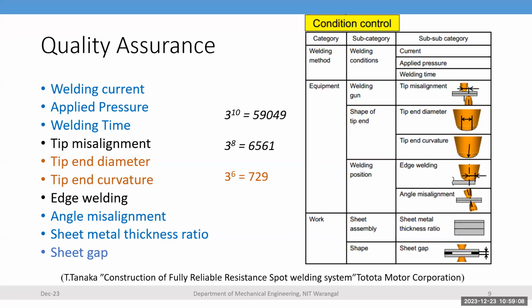Then, with reference to the workpiece sheet assembly, the sheet metal thickness ratio also affects the heat generation of the individual plate. And shape, sheet gap. If there is misalignment between the two sheets, air occupies the space between them. That air is a bad conductor of electricity, so heat is not transferred to the location. That's why sufficient heat is not generated, because the Joule effect is reduced, that is H equals I squared R T. If I changes, there will be a problem. So this is the construction of fully reliable resistance spot welding, Toyota Motor Corporation.